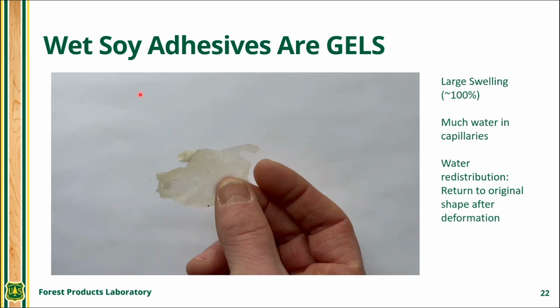So the dry cured protein film is quite brittle, and here I am showing the same film that I put on a glass just before the talk started. You can see what water does to it. Very much changes the physical properties, very high swelling, enormous drop in modulus with water. There's a lot of water in capillaries, and I call these things gels because even with a nanoindenter, they return to their original shape after deformation, which is characteristic of gels. So lots of big capillaries filled with water.